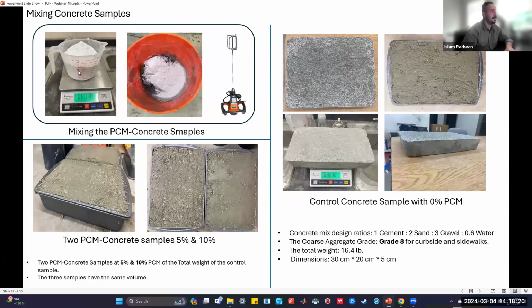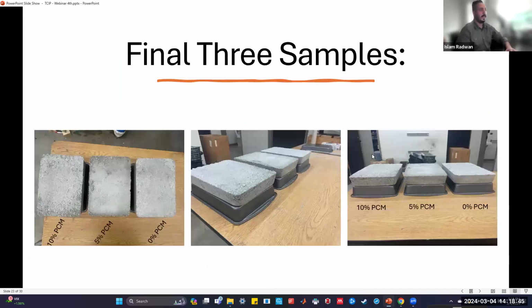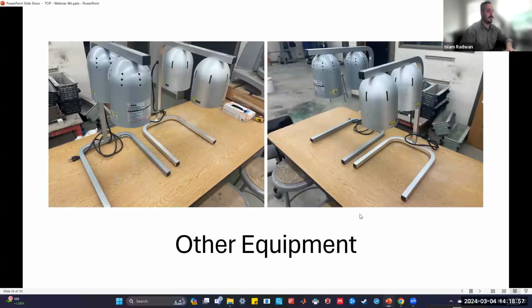As I mentioned, the PCM is in powder form, and we added it at the last step because it was strongly recommended to add the phase change material last in order to avoid breaking the shell of the microcapsule of the PCM. We made two PCM concrete samples, 5% and 10% of the total weight of the control sample. And then we have 3 final concrete samples: the 0% phase change material, the 5%, and the 10%. Okay. And then those are the 2 stands, and each one of them has 2 light bulbs, so for the heating source, as I mentioned before.